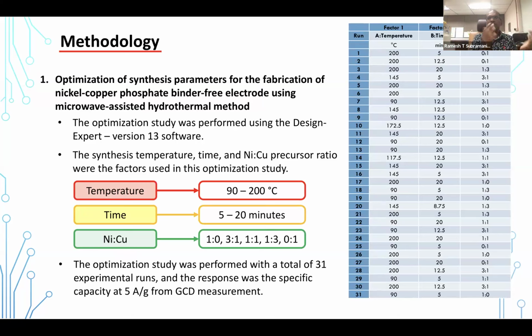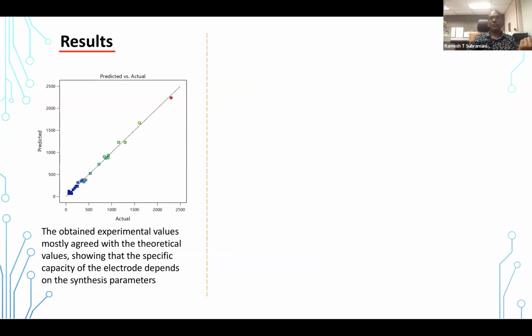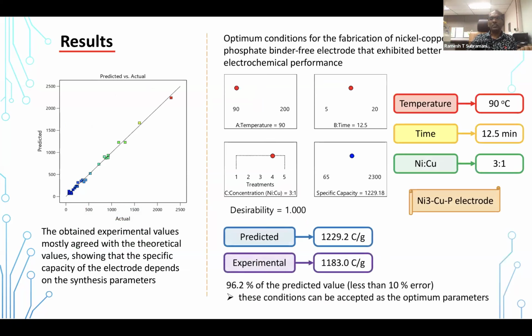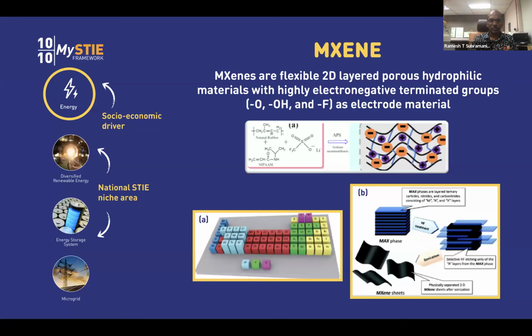Based on these ranges, we do the DOE to find the optimized temperature, time, and ratio. From here, you can find the best formulation: the temperature at 90 degrees Celsius, time about 12.5 minutes, and the nickel copper ratio 3:1. Once we optimize these values, we go ahead with further characterization and formation.